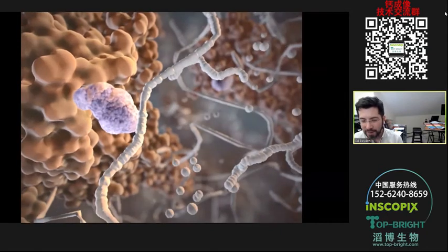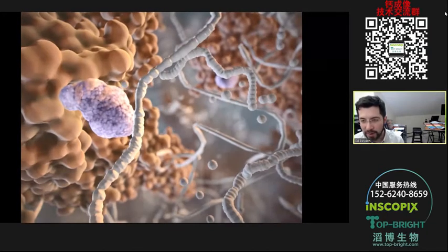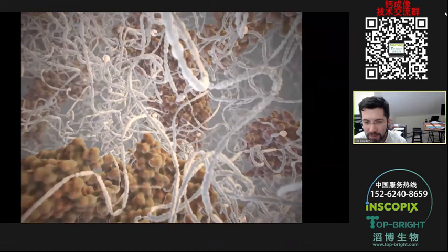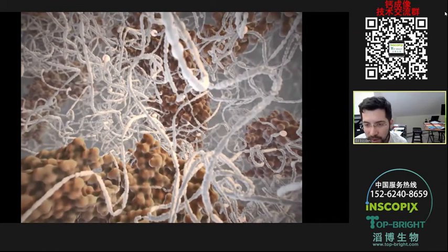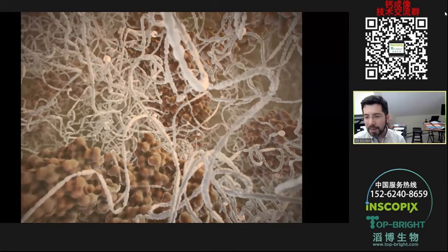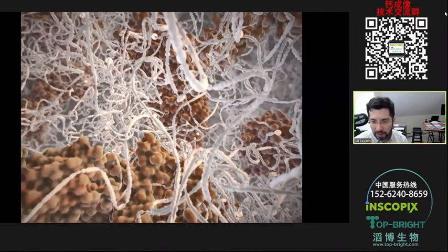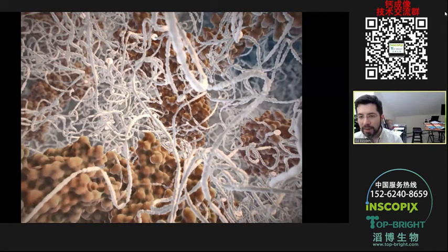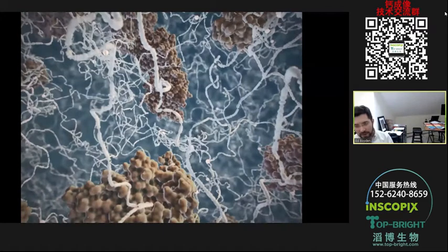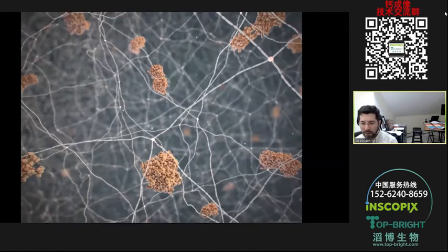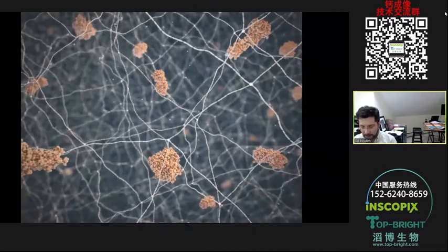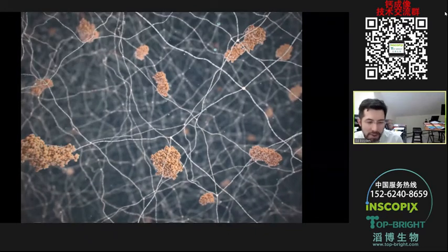And so if you think about it, the polymer threads are swellable. If we add water now, shouldn't it just expand? The polymers absorb the water, the handles bring the biomolecules along for the ride, right? But there's one more step we had to figure out. We have to soften it because things don't like being expanded. So we add detergents, enzymes, and/or heat. And then when we add water, the sodium polyacrylate, the baby diaper material, absorbs the water. But this time, because of the handles, the biomolecules, or labels attached to the biomolecules, will come along for the ride. So we call this expansion microscopy.